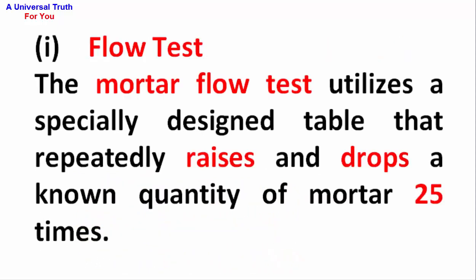Flow test. The mortar flow test utilizes a specially designed table that repeatedly raises and drops a known quantity of mortar 25 times.